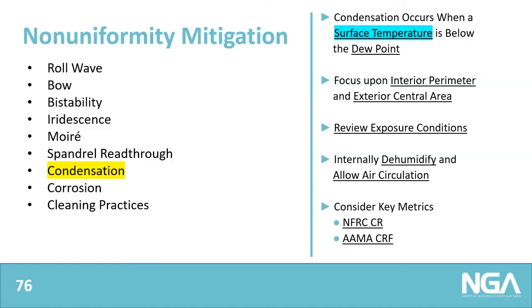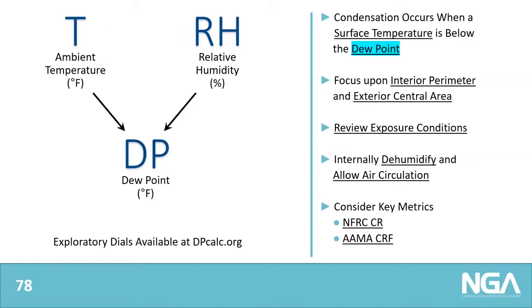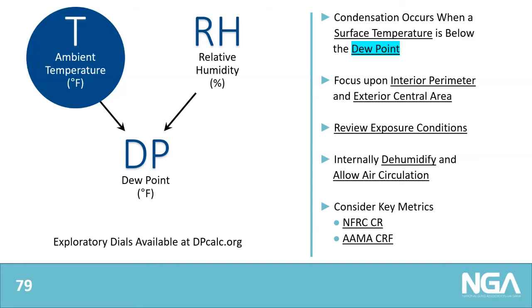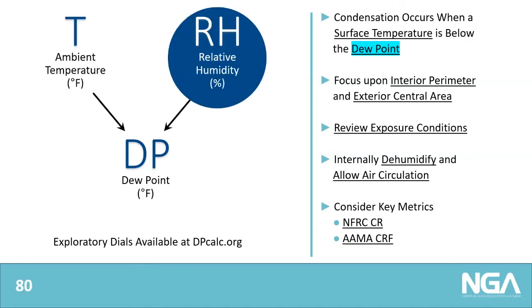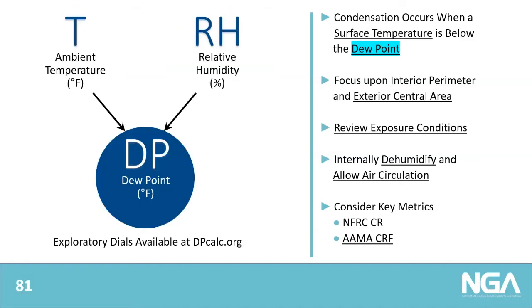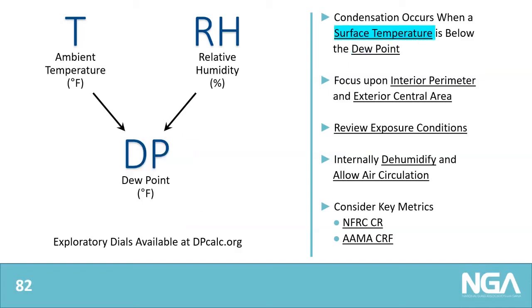Condensation is a situation where a surface temperature extends below the dew point. In terms of the physics, the ambient temperature and the relative humidity together establish the dew point. If either elevates or reduces relative to the other being fixed, then the dew point adjusts accordingly, upward with whichever one is changing upward, and downward if it adjusts downward. Again, the surface temperature extending below the dew point leads to condensation.